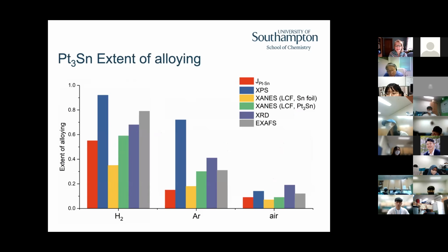Well, each of those measurements gives you a different measure of that. And so by having them all, we can say that if you anneal under hydrogen, you get a pretty good, but not perfect, platinum 3 tin 1 alloy. It's always a little bit tin deficient. If you anneal in air, it's pretty much platinum particles with a little bit of tin oxide. And if you anneal in argon, it's somewhere in the middle.